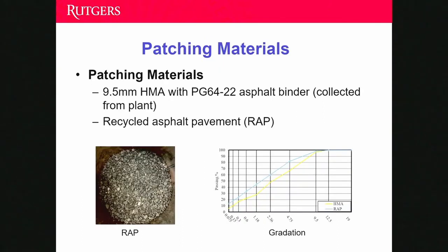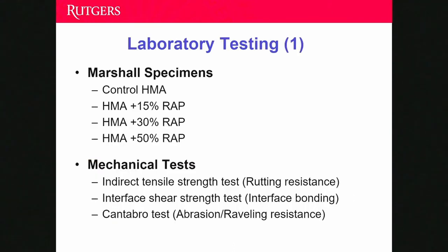In the laboratory, we made the patching material using new HMA and recycled asphalt pavement. The new HMA has a 9.5 millimeter nominal maximum aggregate size, and the asphalt binder performance grade was 64-22. The HMA was collected from the asphalt mixing plant, and the recycled asphalt pavement was milled from different pavements. The first picture shows the appearance of the RAP material, and the second one shows the gradation. Instead of gyratory specimens, we made Marshall specimens because of the large amount of samples we need and the limited material we have. We made 4 groups of specimens: control HMA, and HMA with 15, 30, and 50% RAP.